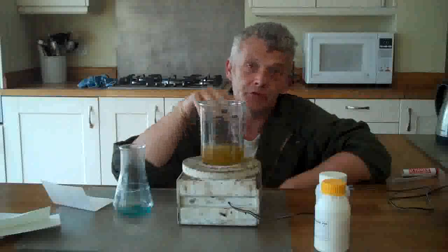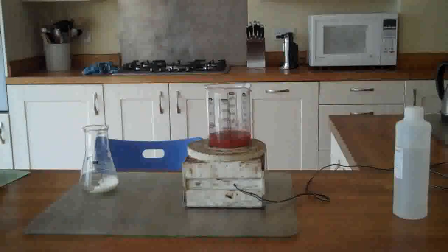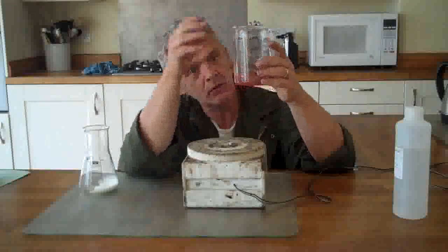You leave this stirring for three hours. After three hours it should have gone through yellow, orange, and bright red. After about three hours of stirring it's gone this nice bright salmon-pink colour — then it's done. What you've got in there is a load of copper nanoparticles covered in PVP to stabilise them. You can get them out by centrifuging, and then use that to make a copper ink. I've included the scientific papers this came from, and the reaction details are all in the description.